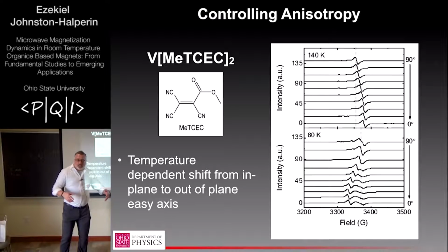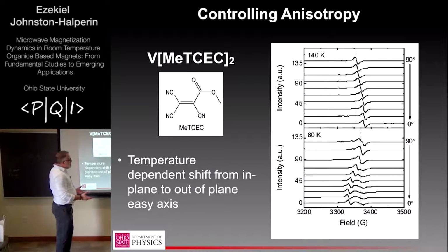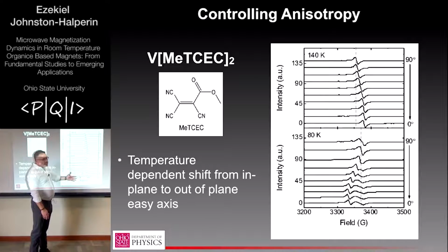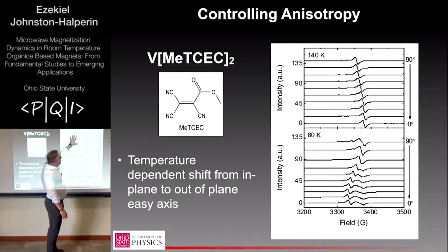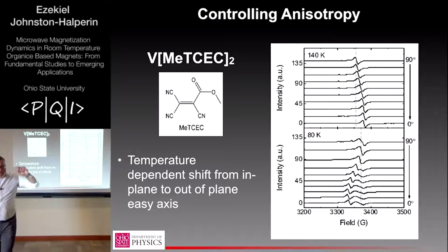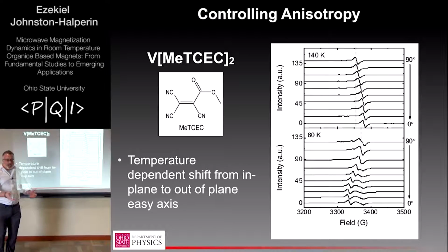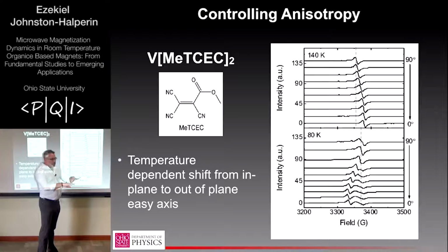So we initially looked at this material as a way to tune the magnetic properties, but when looking at the temperature dependence, we looked at the magnetic resonance as we rotate from in-plane to out-of-plane. At high temperature, this is exactly the shift in center frequency that you expect from this thin film magnetic anisotropy. So as you go to out of plane, you need to apply less magnetic field. Sorry, there's a minus sign there that trips me up every time. Basically, the magnetic resonance is shifted by the demagnetizing field, which provides some additional field on top of the field provided by your magnet. And this shift is consistent with what you expect from a magnetic plate.